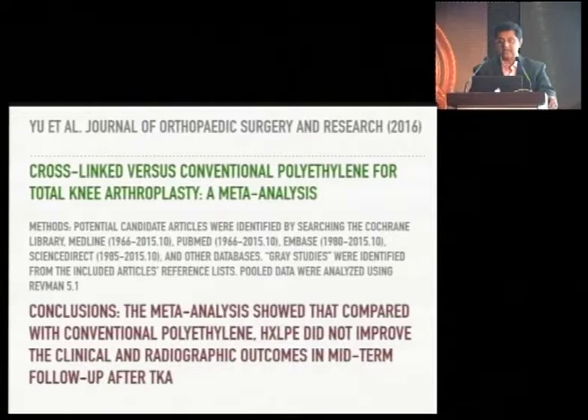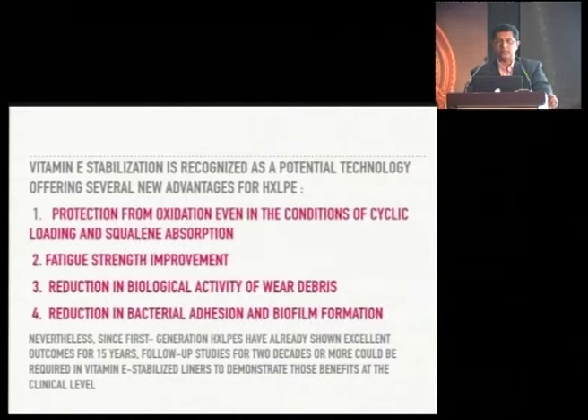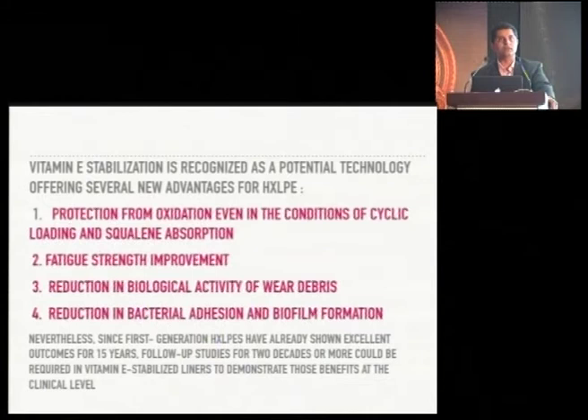Vitamin E was studied by Yamamoto, who said it has several advantages: protection from oxidation under conditions of cyclic loading, improved fatigue strength, reduction in biological activity and wear debris, and possibly a reduction in bacterial adhesion and biofilm. However, vitamin E stabilised polyethylene has only been in clinical use since 2010, so we still do not have long-term data on vitamin E polyethylene.